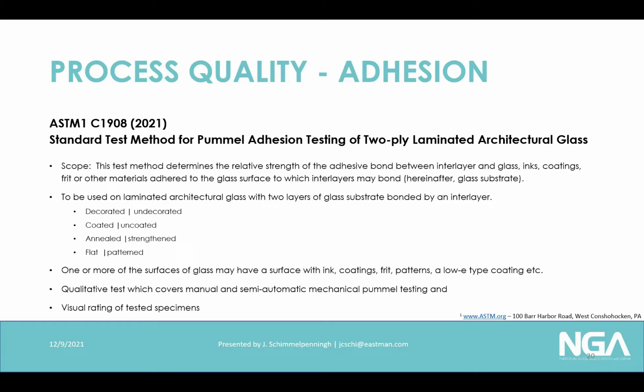So don't think you're going to do this and then go forward. So you have to have specific samples for it. You can use it to look at all different types of laminated glass. Typically 2 layers of glass is where you want to stop because then it gets a little erroneous. One of the surfaces can have anything on it, inks, coatings, frit, patterns, whatever. You will note that because there can be some differences based on those materials and the level of adhesion. It's a qualitative test and it covers both manual and semi-automatic pummeling, and we'll show you that, but it is a visual rating. The test method is a visual rating right now.